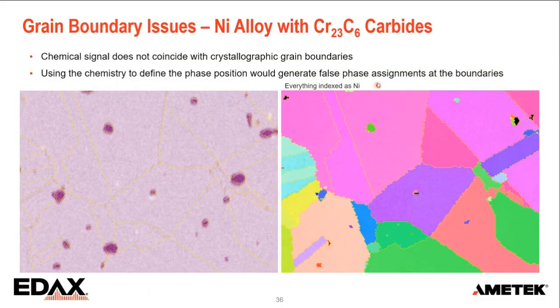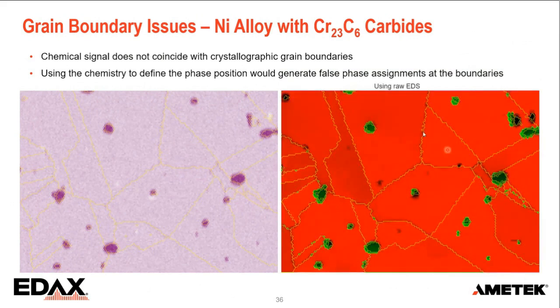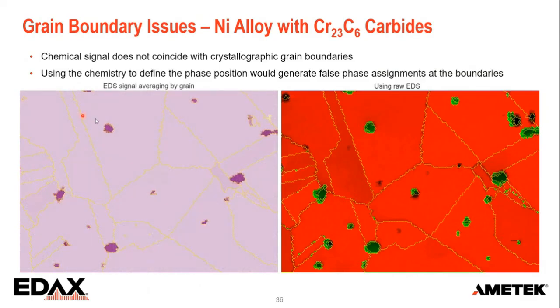When I just index everything as nickel in this case, I can get the grain size, but that doesn't match the chemistry. So if I use the chemistry to assign another phase to it, you can see I get a ring of misidentified points around the particles because the size of the chemistry interaction volume is so much bigger. What we can do then is use the indexing result to average the chemical signal by grain. And when you do that, you get a very sharp